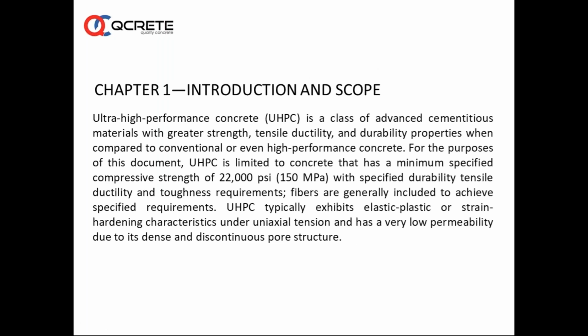Ultra high performance concrete is generally a concrete which is high in strength, 120 to 150. It is limited to concrete that has a minimum specified strength of about 150 MPa with specified durability, tensile ductility and toughness requirements. So high performance concrete, we know what it is: the performance of concrete is defined by its permeability, by its shrinkage characteristics, by its chloride resistance, by its sulfate resistance. Overall, the performance criteria are introduced.